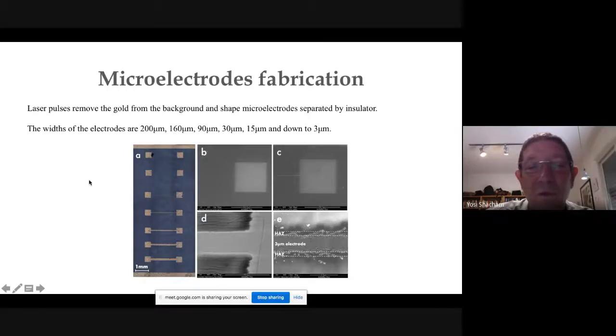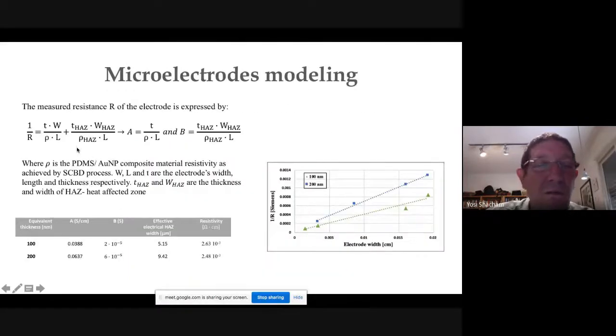This is how it looks. And just to show you that we have working devices, we make electrodes with different widths and measure the resistance. This is 1 over resistance versus electrode width, and we proved Ohm's law: resistance is proportional to 1 over the width of the device. We calculate the specific resistivity, and you can see here it was about 2.6 times 10 to the minus 3 ohm centimeter, which is excellent for electrodes.